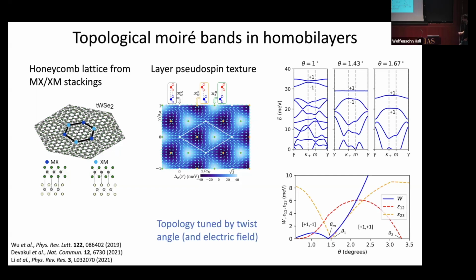So this was theoretically predicted by Alan MacDonald's group first, and here I'm showing some follow-up calculations by Liang Fu and Trithep Devakul, showing that, in fact, as you tune the twist angle in this system, you can change the expectation for the Chern numbers of different Moiré bands for a given valley. So again, very similar to what we heard from Xiaodong Xu's talk. So you can go through this topological phase transition.